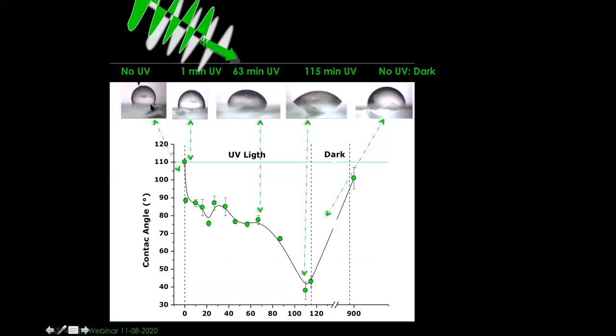At the beginning, there is no UV. As you can see, the contact angle is quite high. And this is without UV. What we do, we shine the surface with UV light. And this UV light activates the zinc oxide. I don't want to go through the physics behind. I don't think that we have the time here.